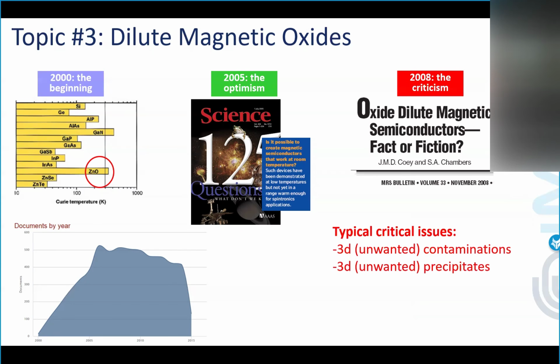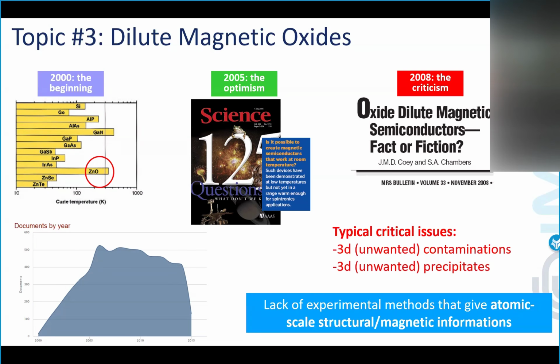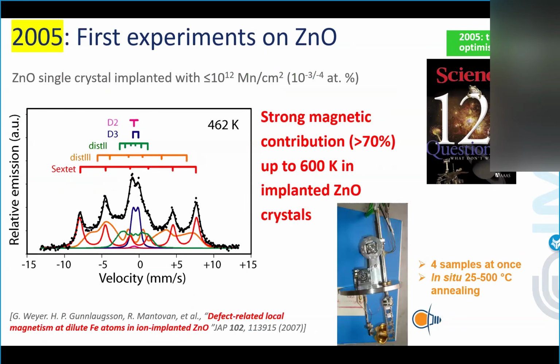And the main problem was that people doing even Mössbauer in the lab, in order to have the signal, needed a fraction and a concentration of magnetic atoms that typically gave precipitates. So at the end, you were looking at magnetism originating from precipitates and not real dilute magnetism as we were hoping, or from unwanted contamination. And there are long stories of handling your sample with improper tweezers and seeing a signal in the SQUID, for instance. So there was a lack of methods that can get rid of this, and we were trying to do something here.